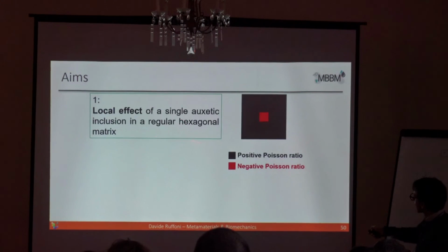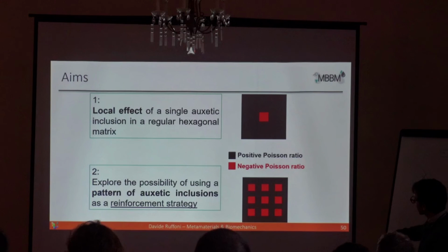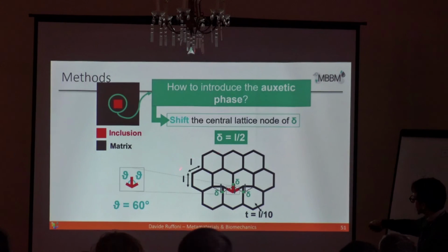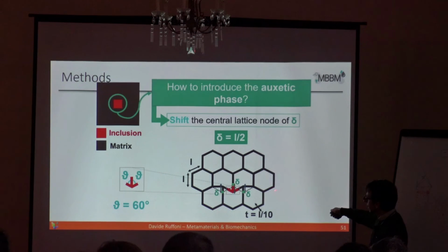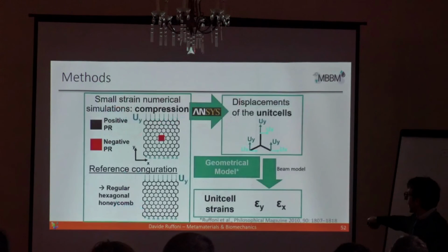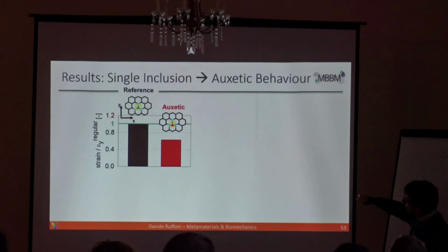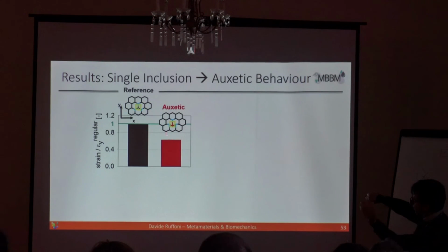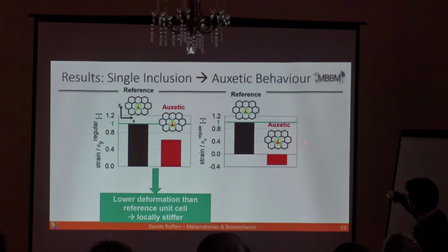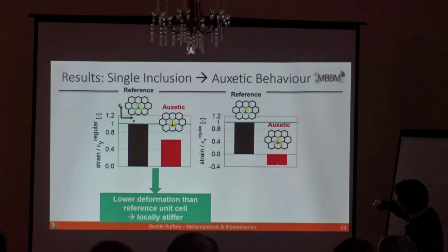So the basic idea is, first of all, to investigate the effect of a single negative Poisson ratio inclusion in a positive Poisson ratio lattice, and then to use a pattern of inclusions to reinforce this. We investigated a system like this, where you have a hexagonal honeycomb, where we change just one single joint to have it as negative Poisson ratio, reentrant if you want. Then we did some finite element analysis, and we saw that if you apply a vertical compression on this large honeycomb, the region with only one node showing this negative Poisson ratio is behaving a little bit more stiff, because its deformation along the applied load is less than the regular case. And if you look at the lateral deformation, it's negative.